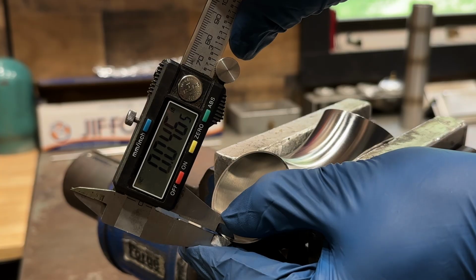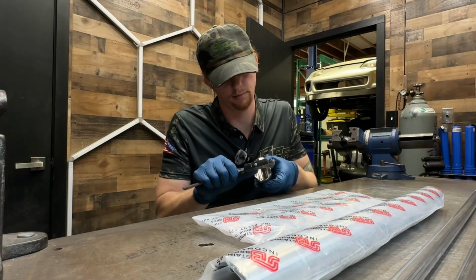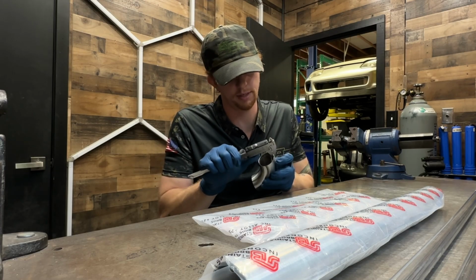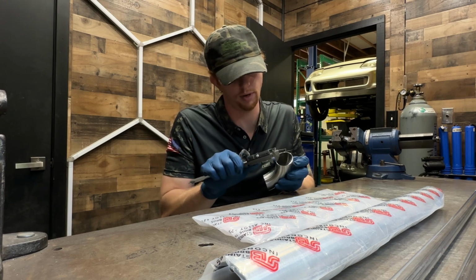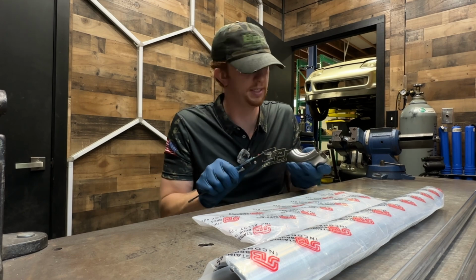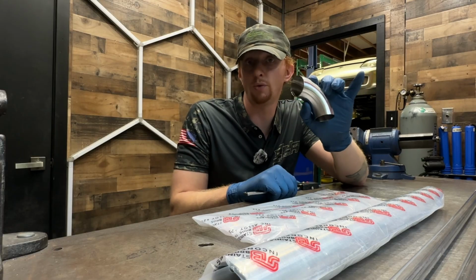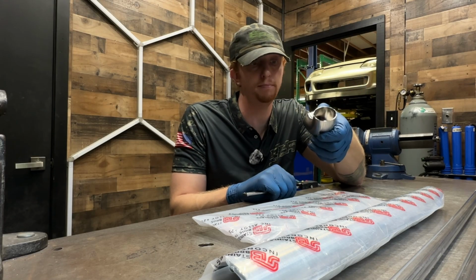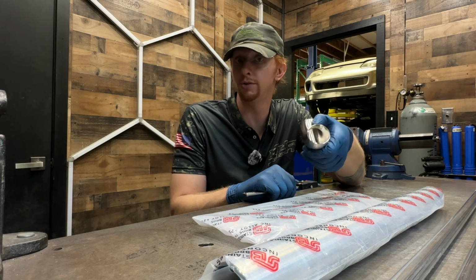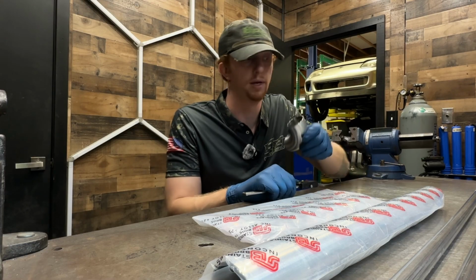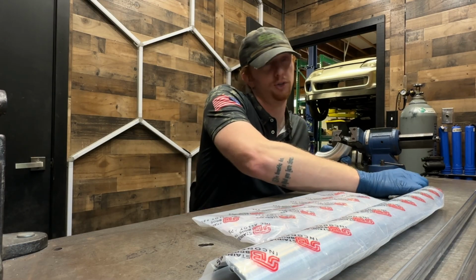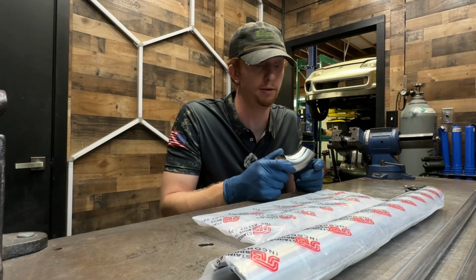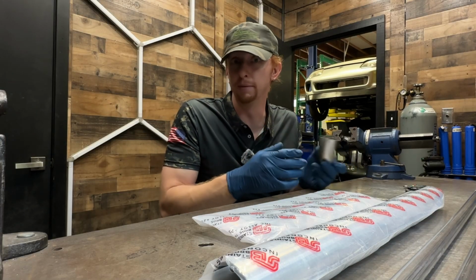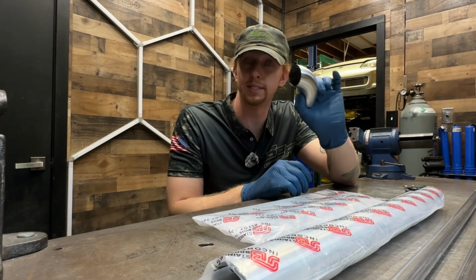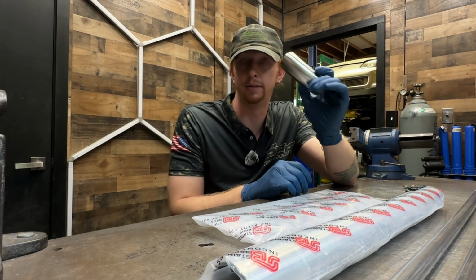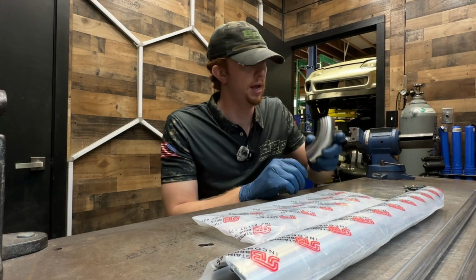On the other side, 45 thousandths, top side 44, bottom side 36. So the thinner the wall thickness that you can run on the material that you're using will equate to a lighter part in general. It's just a simple equation of how much material is actually being used to build the part. And just because the wall thickness is thinner on this material does not mean that it is weaker.